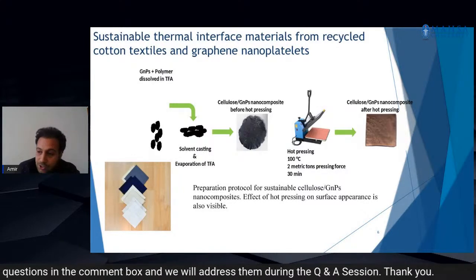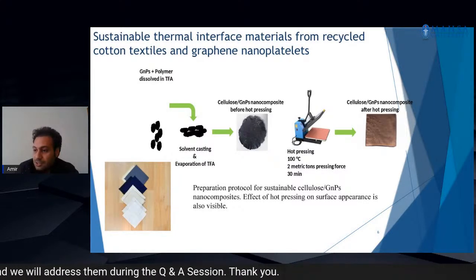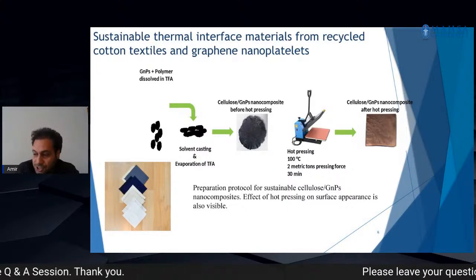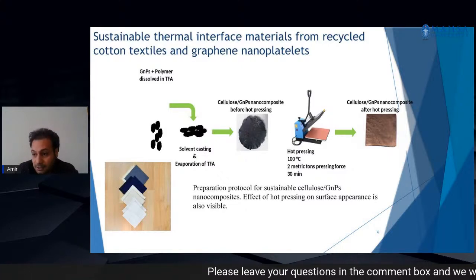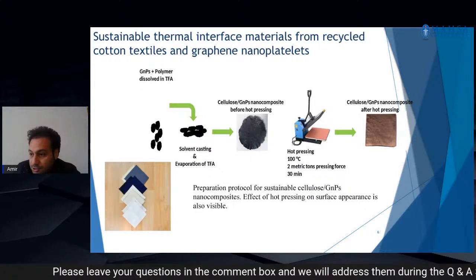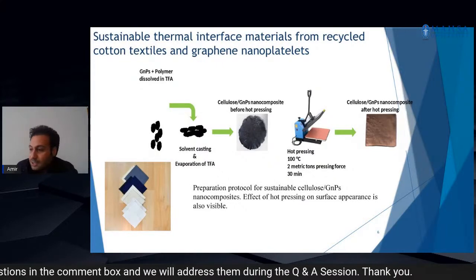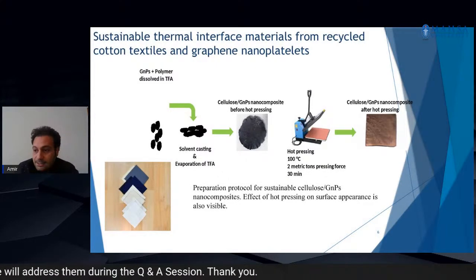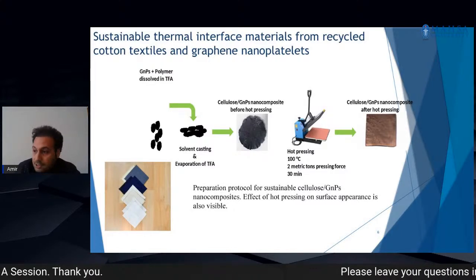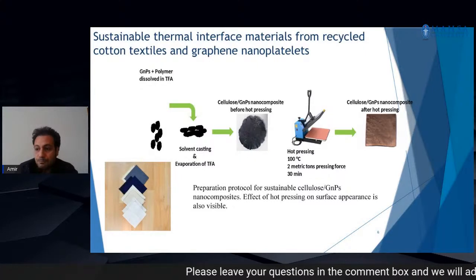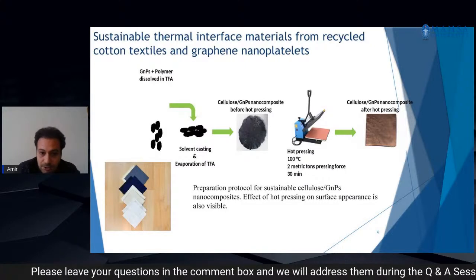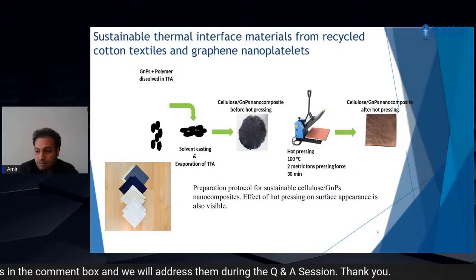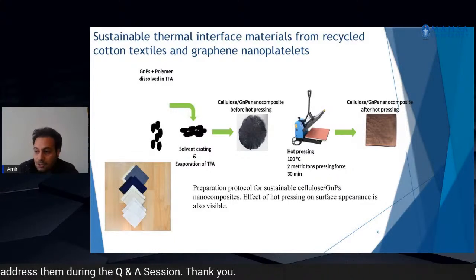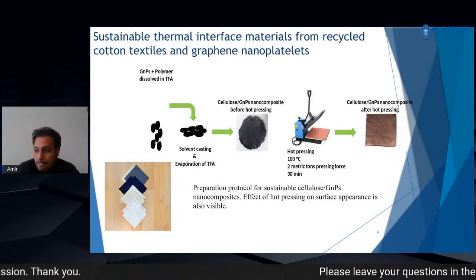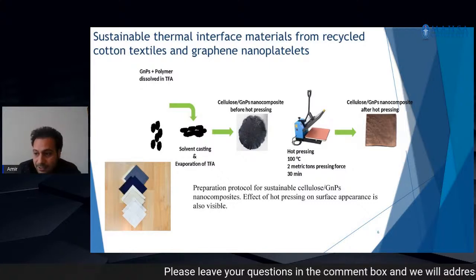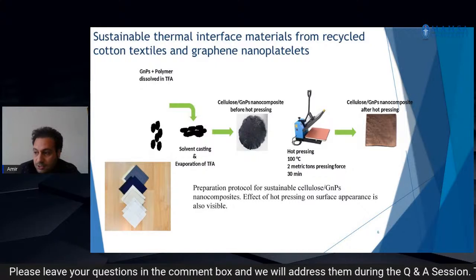So in this project, we report a simple fabrication process of sustainable bio-based TIMs using regenerated cellulose and graphene nanoplatelets, we call GNPs. The process relies on forming conductive inks by dissolving post-consumer cotton fabric and dispersing GNPs in a common solvent, followed by solution casting and drying. You can see on the screen that the material is a plain woven 100% cotton fabric, used as a model cotton fabric for regenerated cellulose composite. And we are using TFA as a solvent for dissolving cotton without further purification.